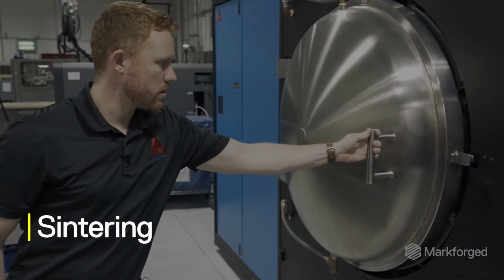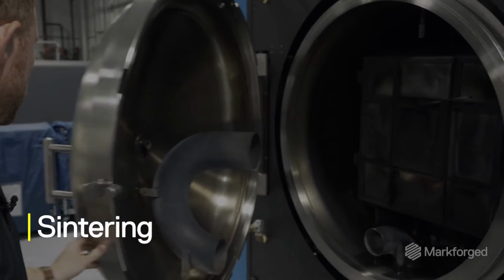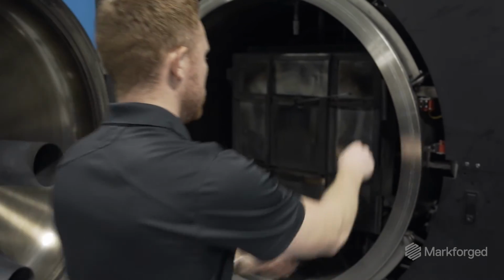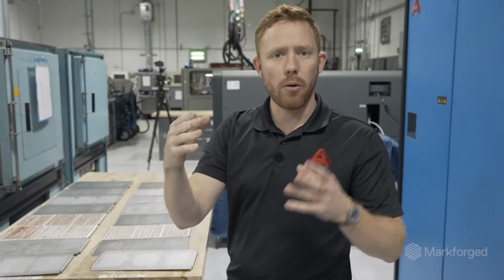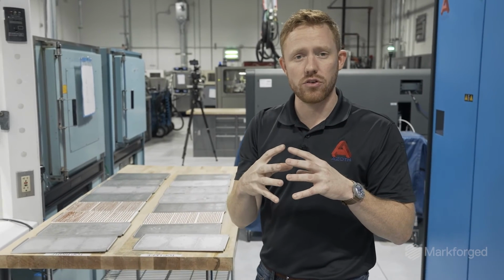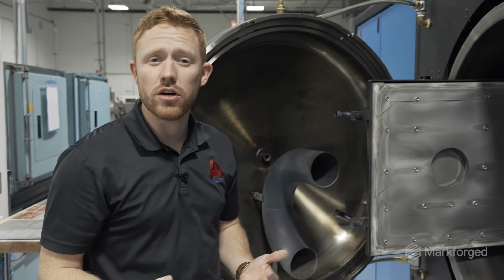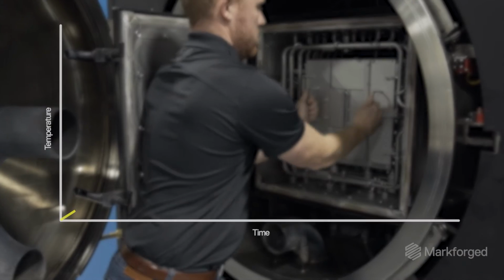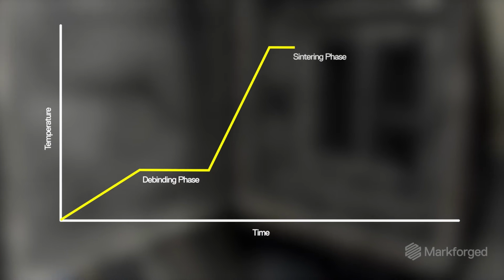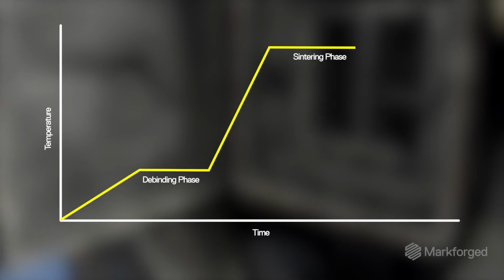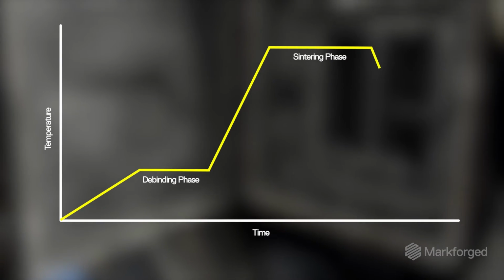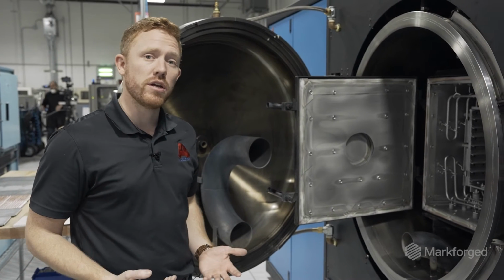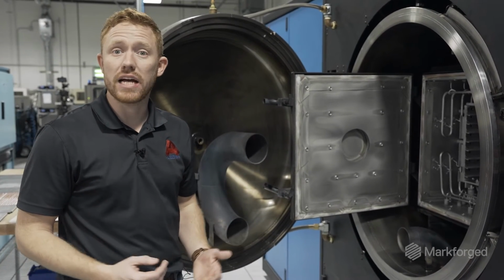Sintering is a thermal process where basically we heat the parts up to just below their melting temperature. The parts will actually densify in every direction, and out comes a fully dense metal part. It's about a 20-hour cycle. The first segment, we remove the binders from the part. The next segment, we ramp up to near top temperature and hold for a prescribed amount of time. The parts will shrink roughly 20% in each direction, and then we'll cool down.